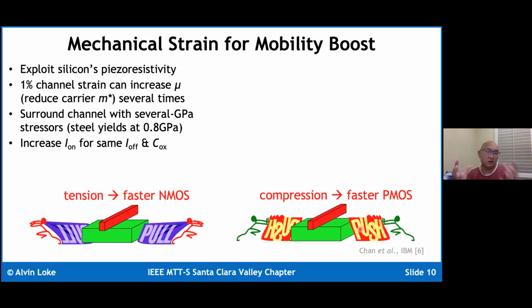Basically, what seems like this ceramic block of material, which looks very stiff and brittle, it turns out that if you can induce 1% channel strain in the lattice, you can actually increase the mobility, or another way of saying, reduce the effective mass of the carriers by several times, which directly translates to several times increase in current. Okay. Now, unfortunately, because silicon is this brittle ceramic kind of material, it has a very high Young's modulus, which means that you need to have extremely high stresses, on the order of several gigapascals, stressing it with gigapascal materials around in order to get that 1% channel strain. And just as a reference, steel will yield at about 3/4 of a gigapascal, and we are routinely straining our transistors at several times that, just to give you an idea.